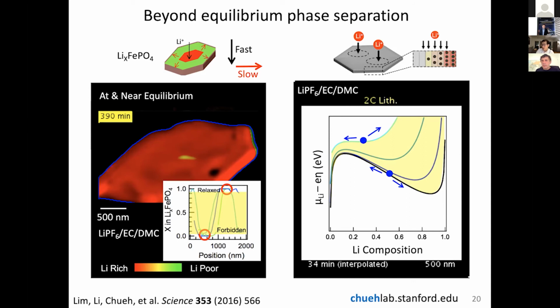So what I'm showing you here is that the autocatalytic effect, the fact that the kinetics strongly changes with the composition of an ion insertion material like lithium iron phosphate, when you apply a current to the system, you can actually get the system to behave in a completely non-equilibrium manner. So this is the explanation behind why the system phase separates normally at a low rate, but it doesn't phase separate at a high rate, which again is something that is quite unusual and has been noted many times before, but it was not until recently we have a complete explanation for what is happening.